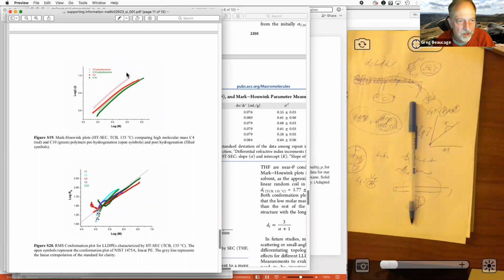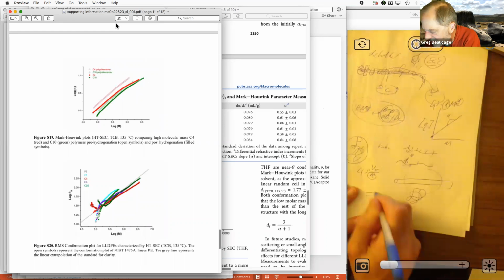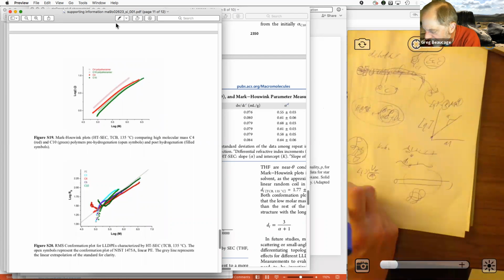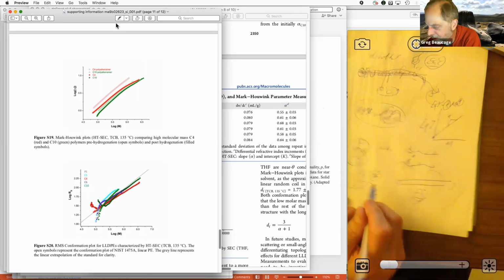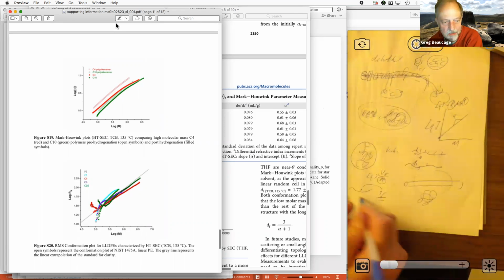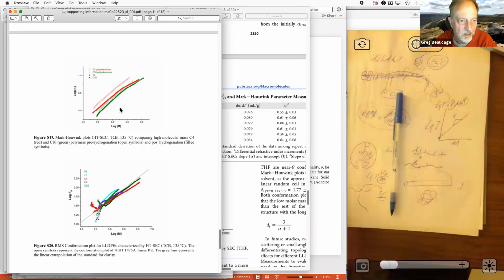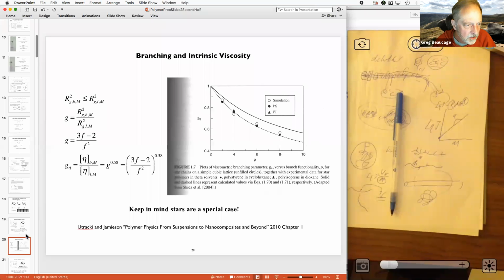So that's because they're getting this long chain branching, because when they are hydrogenating the double bonds, or putting it through this high temperature pressure hydrogenation, they're making some free radicals, and then those are bonding up to make branches, long chain branches that are showing up in the intrinsic viscosity that way. You can see that. Let's see this. There's a picture of that somewhere here.